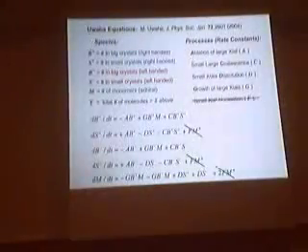Okay, then what processes? There's ablation, knocking pieces off the large crystal. The coalescence, that's the crucial one. Homo coalescence faster than hetero. Dissolution of the small crystals, growth of the large crystals, so communication with solution. And then nucleation of small crystals, which may or may not be relevant. So then these are the differential equations, just for those processes with these materials. And that's the model, except that we're ignoring the nucleation of the small clusters. I doubt that they're relevant.